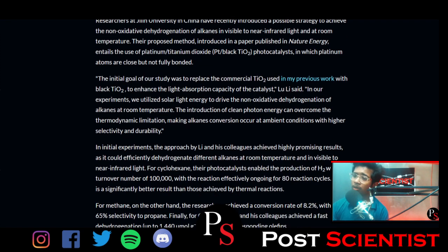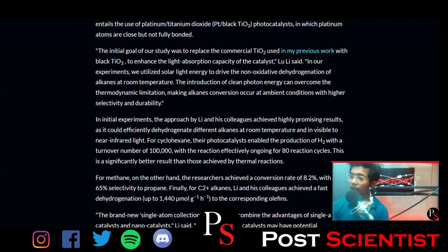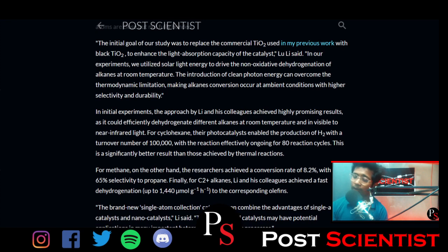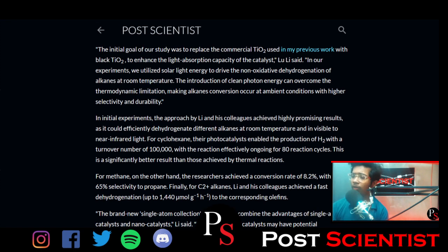Their proposed method, introduced in a paper published in Nature Energy, entails the use of a platinum titanium dioxide (Pt/black TiO2) photocatalyst, in which platinum atoms are close but not fully bonded. The initial goal of our study was to replace the commercial titanium oxide used in my previous work with black titanium oxide to enhance the light absorption capacity of the catalyst, Lu Li said. In our experiments, we utilized solar light energy to drive the non-oxidative dehydrogenation of alkanes at room temperature.